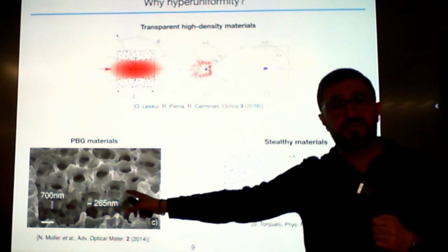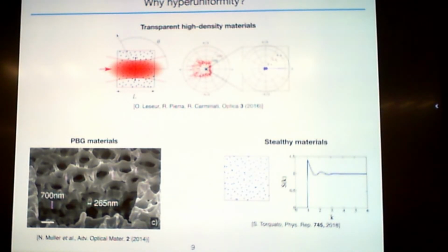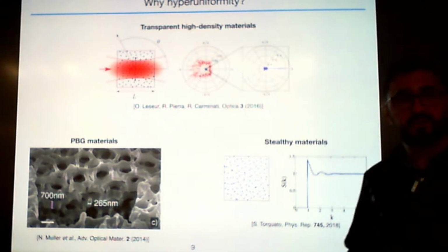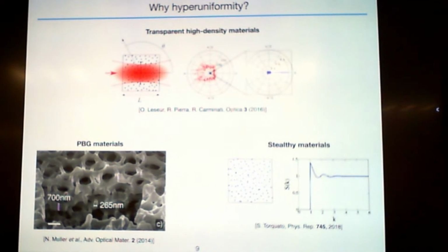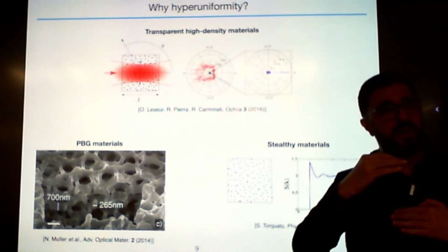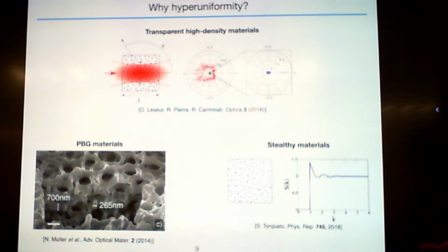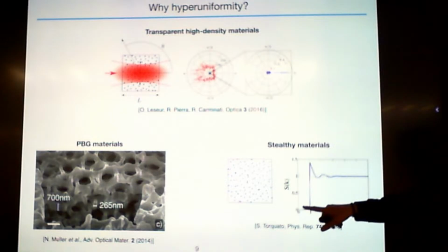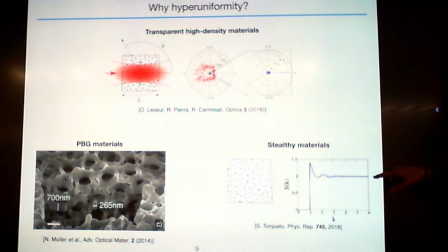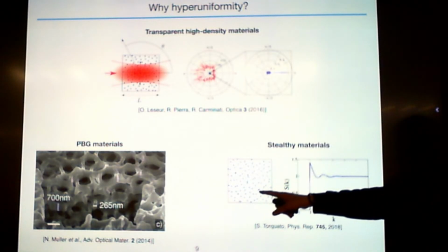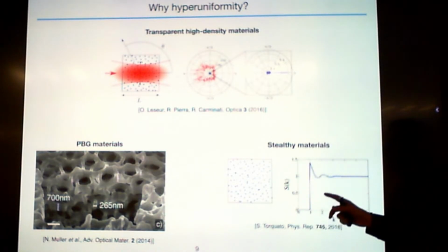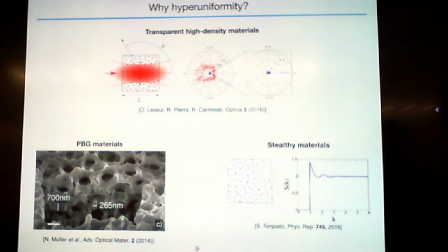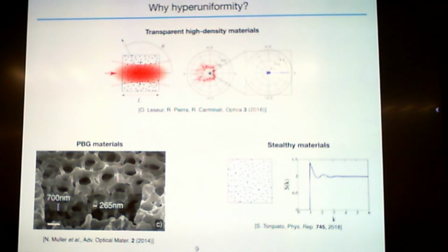For instance, photonic band gaps. This is quite crazy because typically people thought the band gaps can occur only in crystalline materials. But it turns out when you are hyperuniform and disordered, somehow there is some short-range order which is mimicking the crystalline short-range order. But you can open the band gaps, at least in the photonic region. Or you can create stealthy materials. This is inverse. What you do is you assume a structure factor which is 0 up to a certain value and then some form. And then from that structure factor, you inverse engineer a point pattern. Now this point pattern is transparent to incident light below this k. So there are, of course, patents about this. And yes, there are some optical properties that might have potential use for these hyperuniform systems. But as I said, my interest is mainly in the fundamentals of these hyperuniform systems.